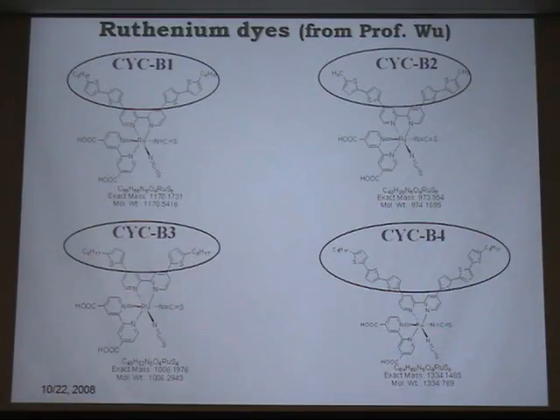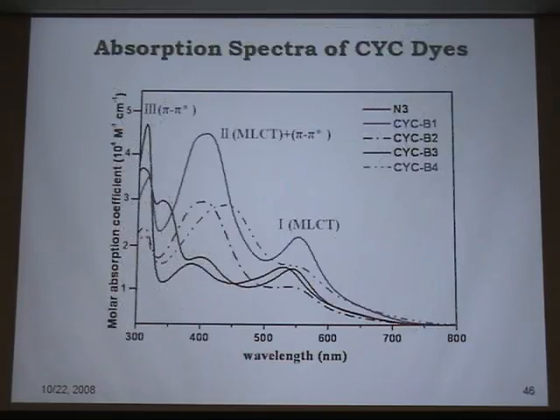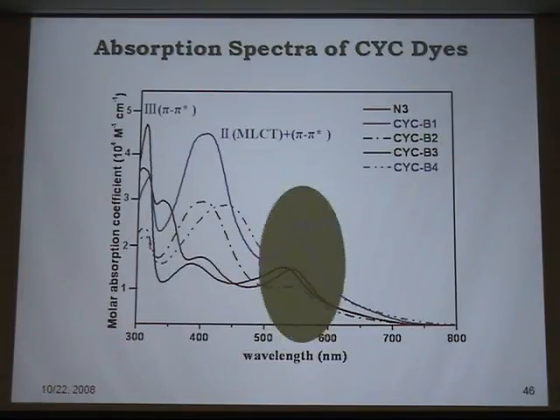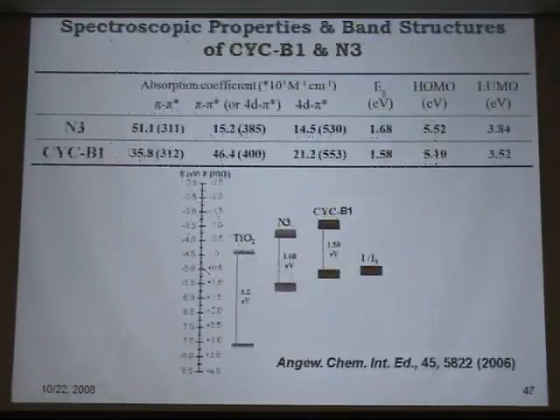Again, this is ruthenium, and the difference is here. Now, this dye, CYCB1, is so different compared to all the others. So we think this should give you the best performance as far as the metal to ligand charge transfer is concerned. Again, we did some HOMO and LUMO. There's not much difference between this and this. But if you look at the performance,